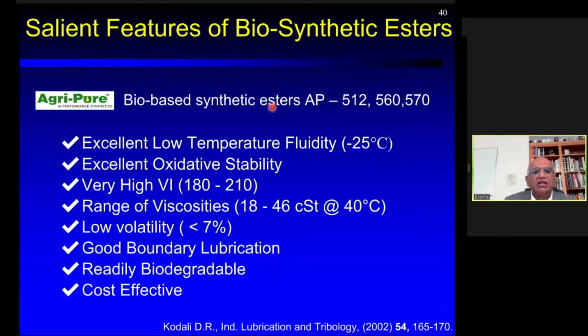These provided the right features that are functional as lubricants. The salient features of these molecules are shown here. They showed excellent low temperature fluidity up to minus 25 degrees. They have excellent oxidative stability, a very high viscosity index, and a range of viscosities depending upon which polyol ester has been used, and also the stoichiometry of the reacting materials. They showed low volatility, good boundary lubrication, and they are readily biodegradable, and they are cost effective as well. So that is a successfully commercialized example.